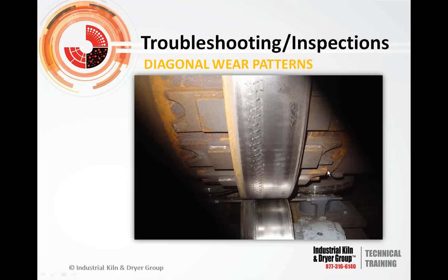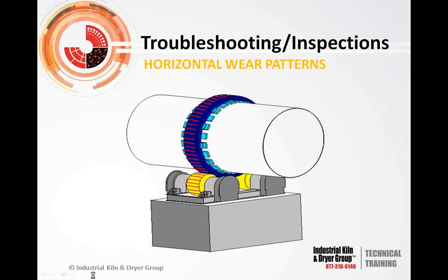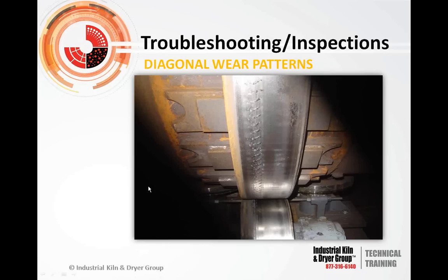For example, if they really push in hard on one roller, not on the other roller, or if you pigeon-toe the rollers like we showed in that diagram, where the shafts of the rollers are not parallel to each other, then basically you'll get this type of thing, and it's usually an excessive adjustment thing. But if you see that type of wear right away, you're going to know that you've got at least one roller that's misadjusted. If you see that, you should go to the control room right away, because you'll probably also see a sharp spike in the motor amperages in the control room. And that would be an indication that you need to get out there and make some adjustments.